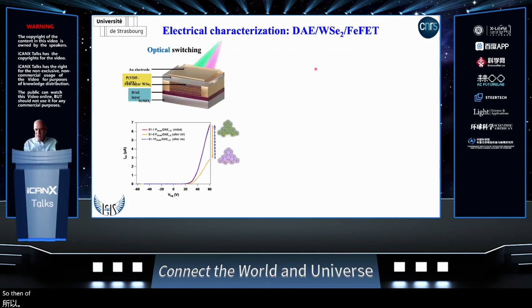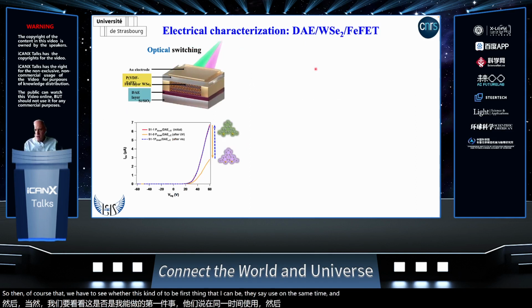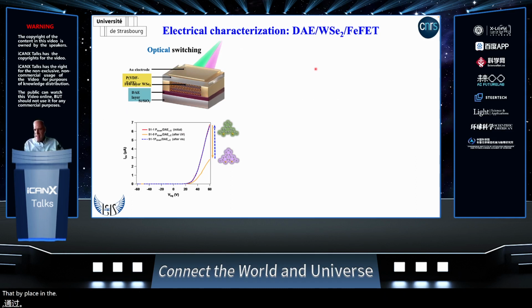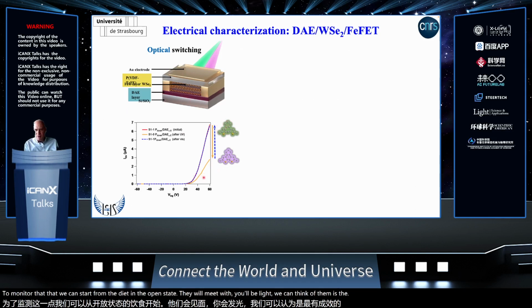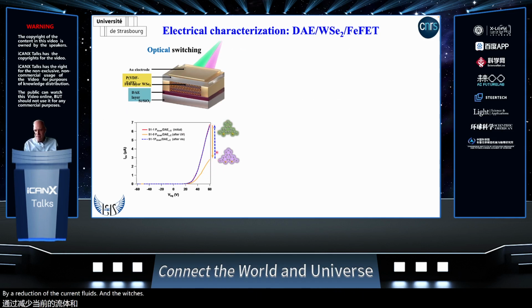Then, of course, we have to see whether these two different stimuli can be used at the same time. First of all, we were not certain that, by placing the diarylethene underneath the tungsten diselenide, we could still trigger its isomerization. So we were very happy to observe that we can start from the diarylethene in the open state, illuminate with UV light, and trigger the isomerization from the open to the closed state. This is accompanied by a reduction of the current through the junction, which is reversible upon illumination with visible light.